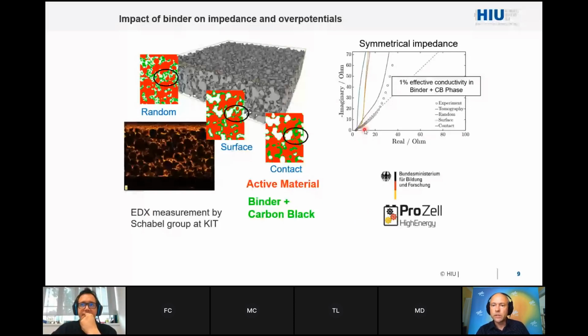So again, the blue one is the pure tomography without binder. The random one, and mostly also the surface one, is nearly blocking, and only those which are concentrated in the contact were getting close to the experiment. So it was obvious that this macroscopic measurement signal was able to say something about what is going on microscopically in the electrode.